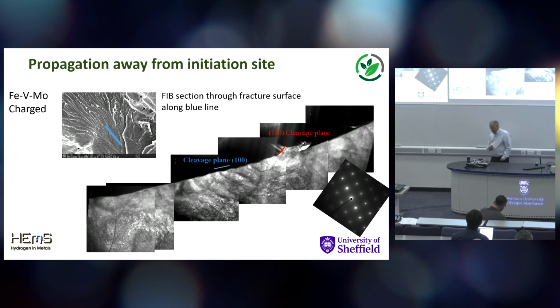As we go away from the crack initiation site, you can follow the crack plane, which is here. As I said, it generally goes along the 100 plane, but there's this series of ridges which are associated with where the precipitate lines come up, and they clearly distort the crack propagation direction. Locally, it switches to a 110 cleavage and then switches back again.